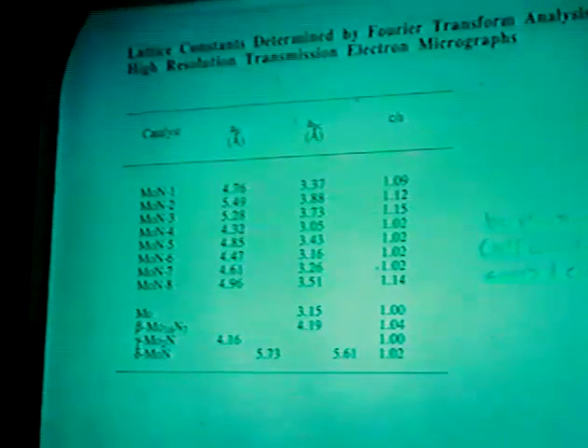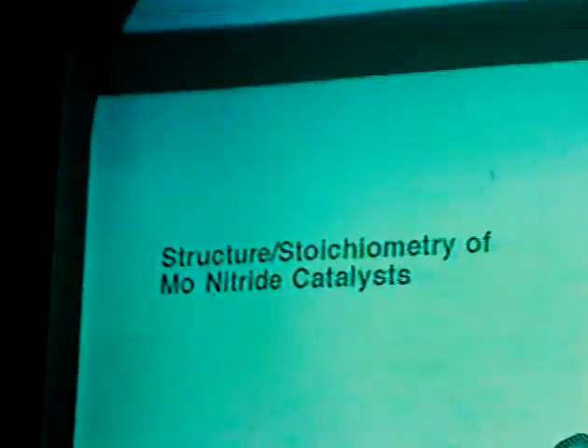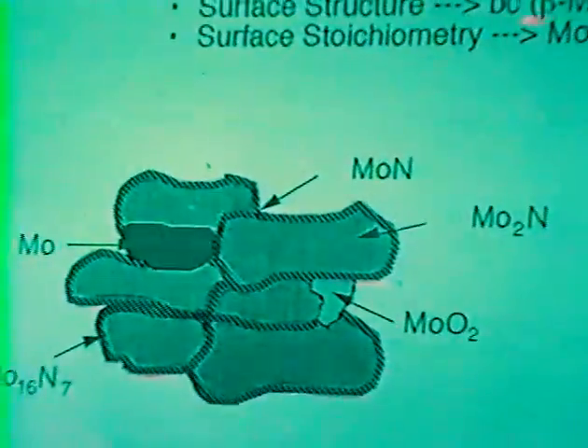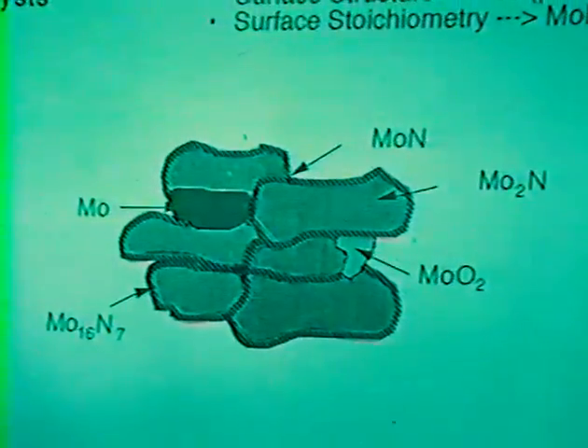The lattice constants that are listed here are bracketed by those of the equilibrium body-centered structures, moly, which is BCC, and then this beta phase, which is body-centered tetragonal. This might suggest that, well, obviously the lattice constant is varying while the structure remains constant, but it may also be an indication that the nitrogen to molybdenum content has caused some change in the lattice constant of the structure. And this is not unexpected. As we increase the amount of nitrogen in the lattice, we should expect that the lattice will expand.